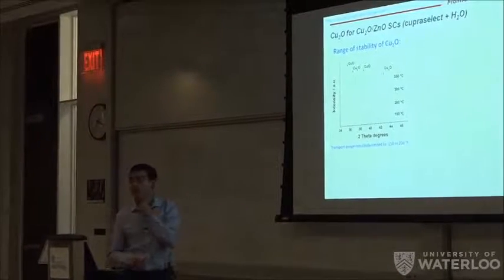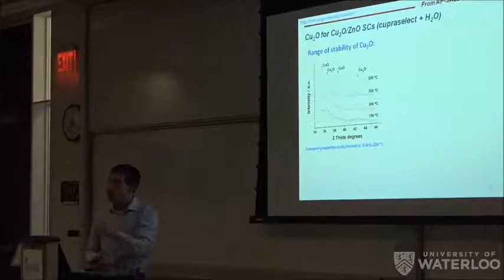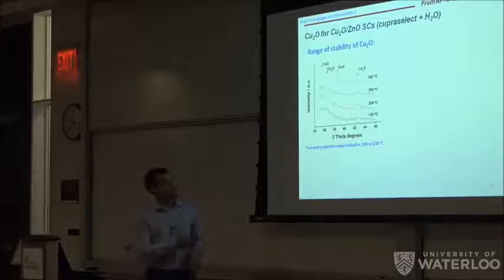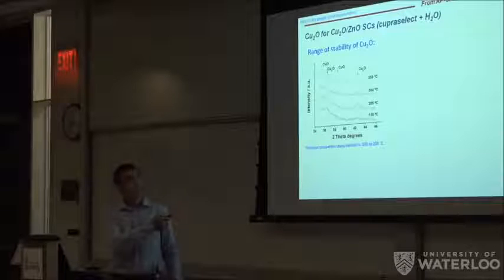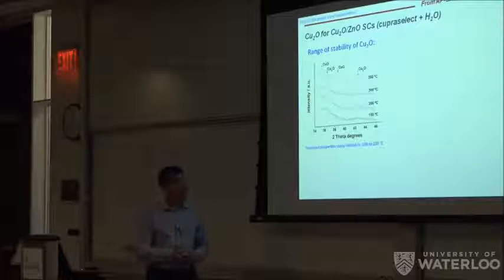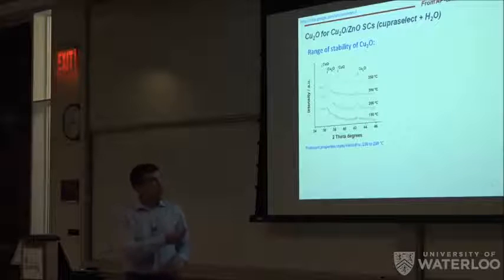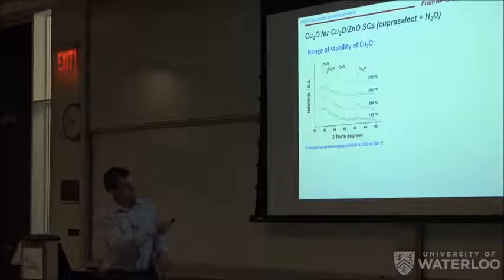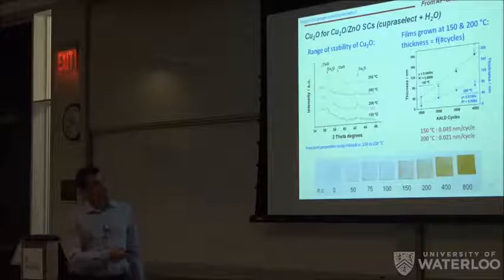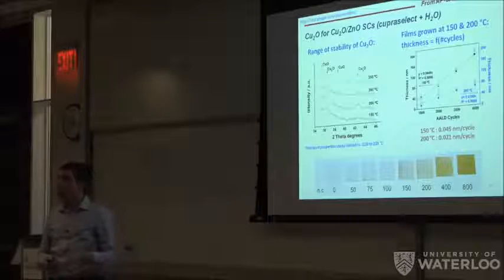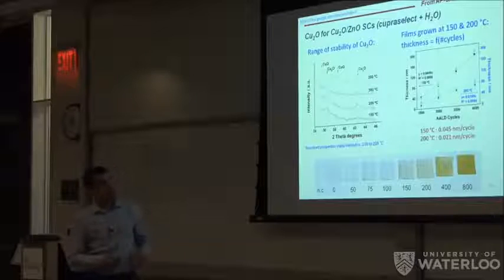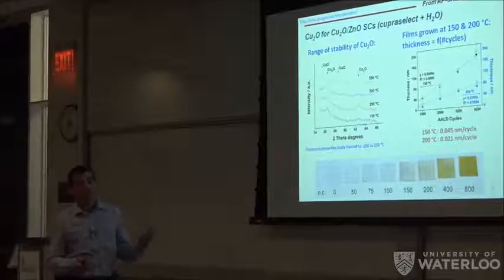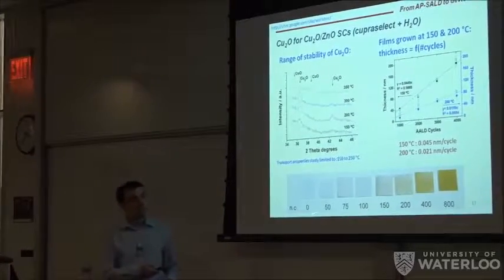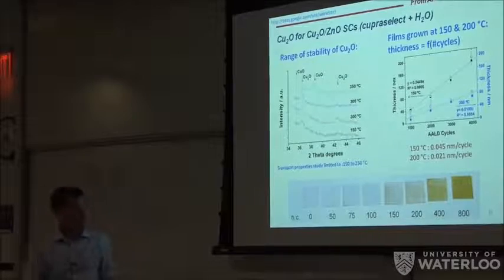What we tried to do was to grow this material with the spatial atomic layer deposition approach, to see whether we could improve the efficiency of the system and the properties of the cell. And then we optimized this deposition using this Cupraselect precursor, which is a commercial copper +1 precursor, reacting it with water. We managed to establish the temperature window of stability below 300 degrees. And basically, we can see that for two different growth conditions, we got different growth per cycle, but it's still proportional. So we are still in ALD-like conditions, even if it's a bit of CVD. But you can see that depending on the number of cycles, we got a particular thickness.